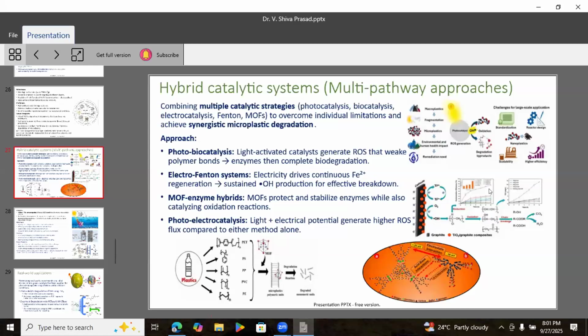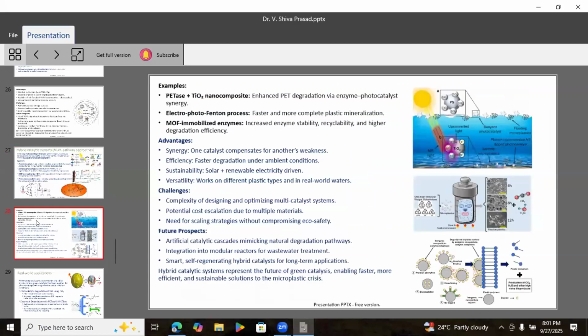With the hybrid photo plus electrocatalysis, light plus electrical potential generate a higher ROS flux compared to either method alone. For example, PETase plus TiO2 nanocomposite enhanced PET degradation via enzyme and photocatalyst, and an electro-photo-Fenton process gives faster and more complete plastic mineralization. MOFs and immobilized enzymes increase enzyme stability, recyclability, and degradation efficiency. The advantage with the hybrid system is that one catalyst compensates for another's weakness, so faster degradation under ambient conditions.